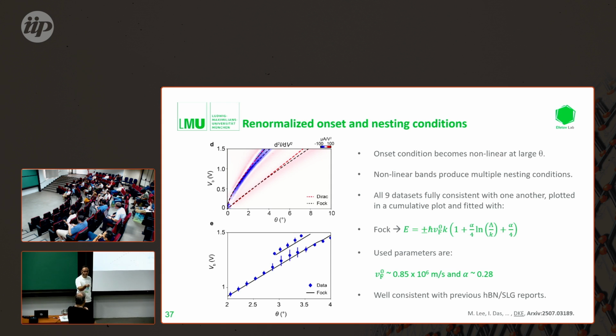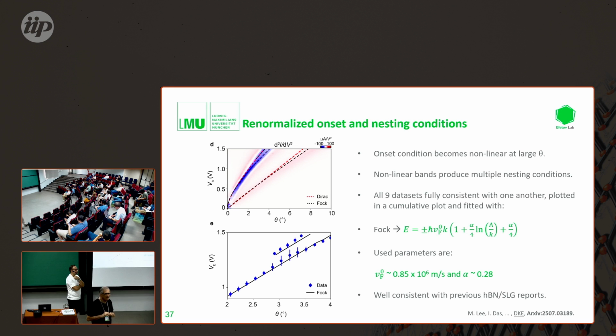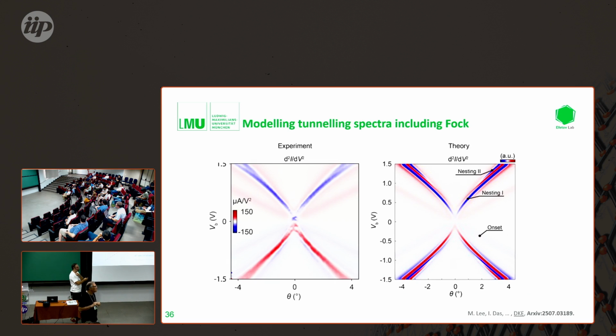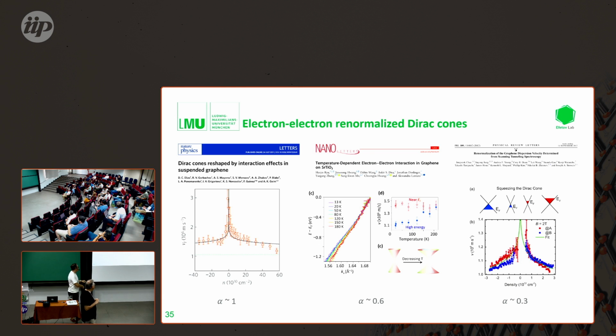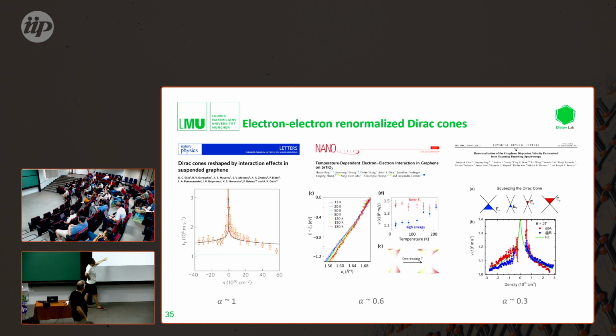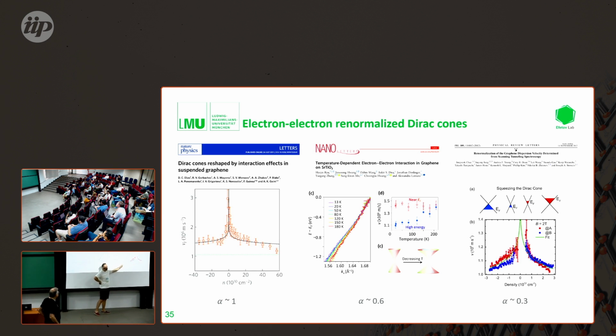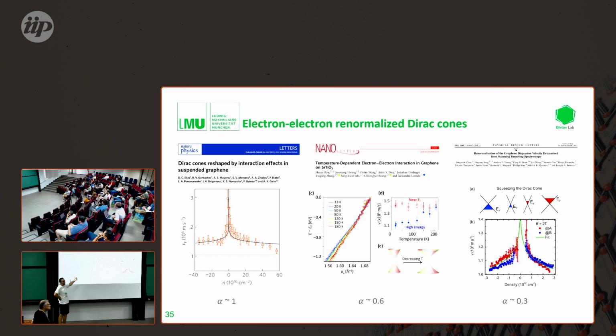It's in the order of the bandwidth of single-layer graphene. But this is a literature value, this lambda, right? Okay, so the difference between those three measurements: this is suspended, this is on STO, which is ferroelectric, and this is on hBN. So those are three different dielectric environments.